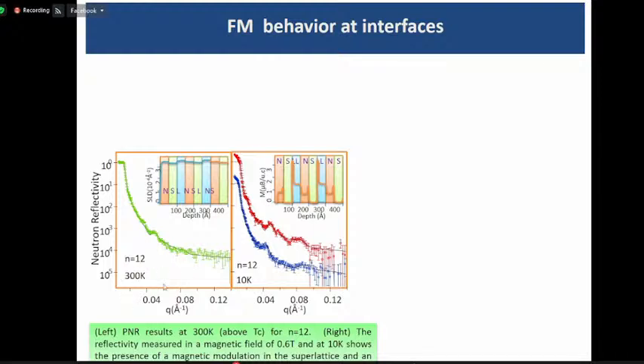Okay. 300 Kelvin is over the Curie temperature, and 10 Kelvin is below the Curie temperature. At 300 Kelvin there are no peaks, but below the Curie temperature you can see some peaks. This peak is due to the magnetic properties at the interface. It should show very clearly like this. So from this data, we said this ferromagnetism is from the interface.